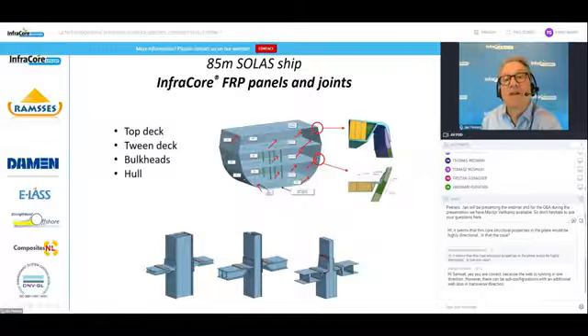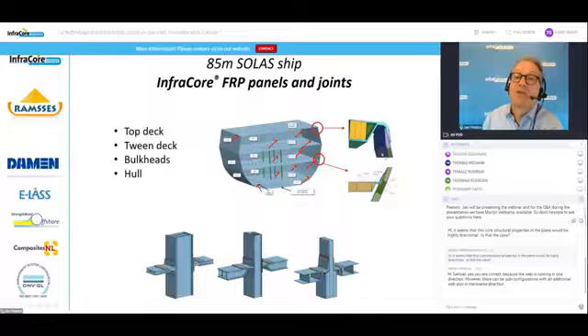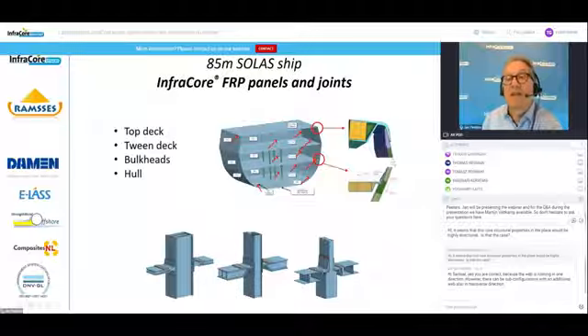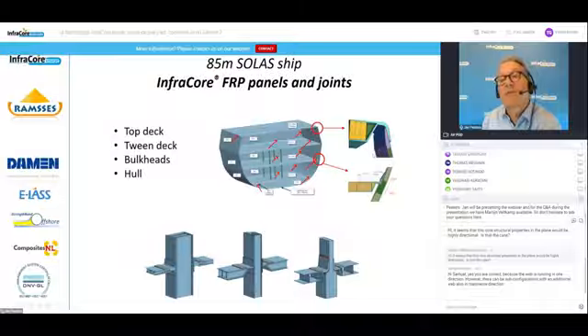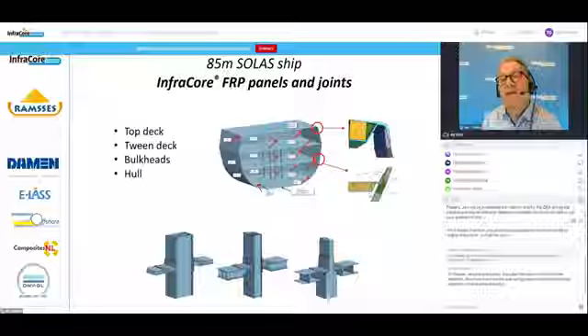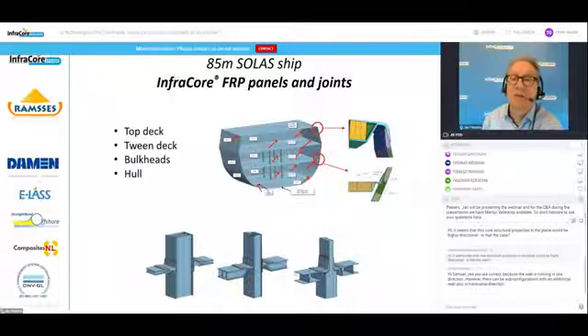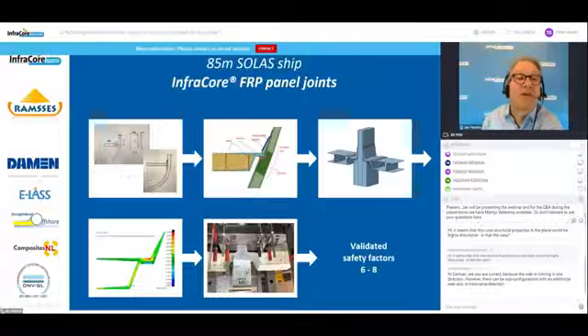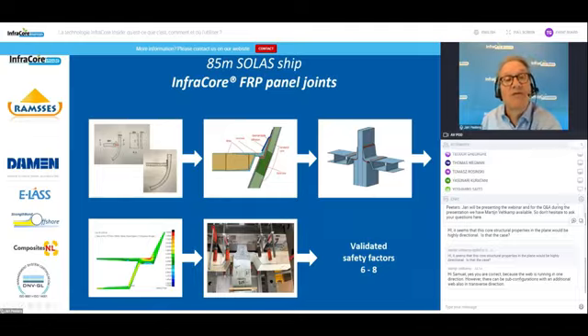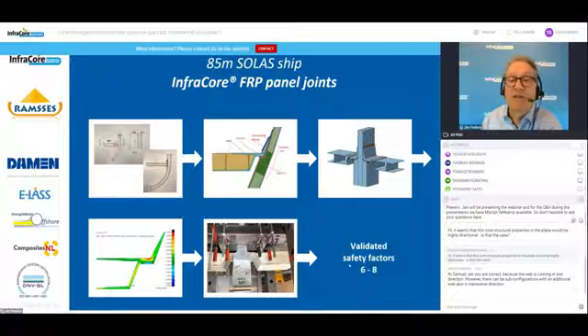So this is the cross-section of the ship, and we've been focusing on developing these joints. And these are InfraCore joints, in this case, to a classic sandwich laminate. And as you can see, we developed flexible joints with which we can absorb some bending stiffness. These are some designs. And this is the classical trajectory which you run through from concept to cut models to a finite element model and up to the final testing which we did. And we certified these joints with a safety factor between 6 and 8.